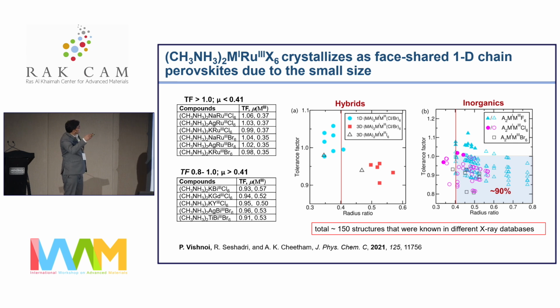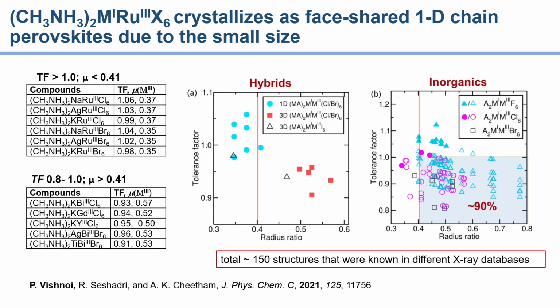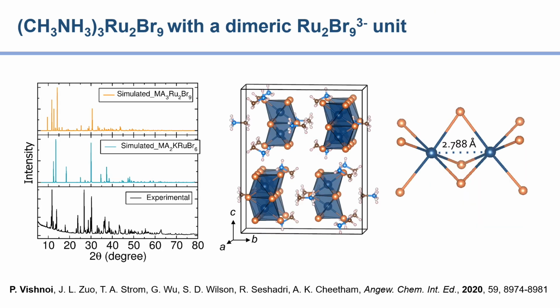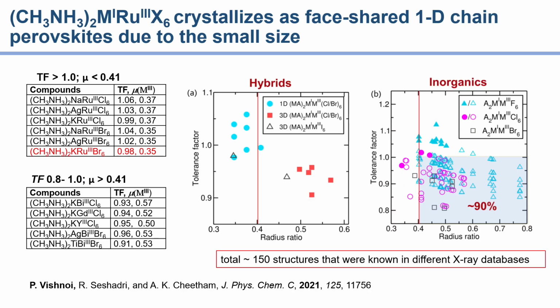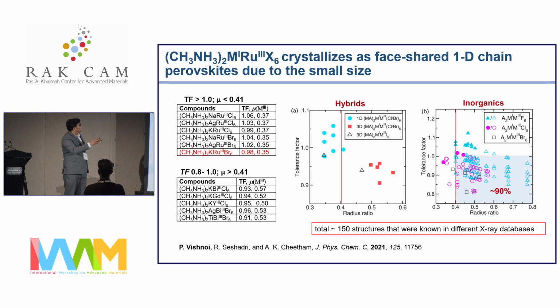So these are the compounds which are one-dimensional. We see that the tolerance factor of these compounds is slightly more than 1, not too high. And the radius ratio is less than 0.41. 0.41 is nothing but root 2 minus 1, which is the condition for a system to form 6 coordination geometry. So we see these parameters are kind of off to form 6 coordination geometry.